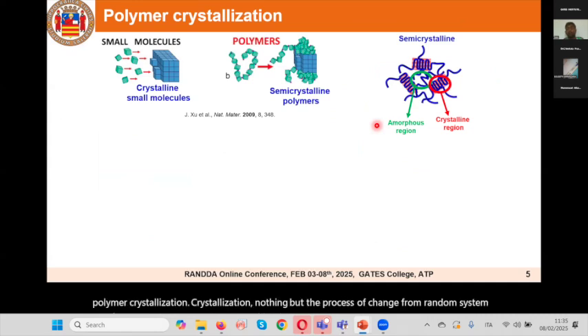That is called crystallization. Crystallization is a process completely different from small molecule to polymer. In the small molecule, crystallization is very simple because the smaller molecule has a very low energy barrier, so it can crystallize completely into a well-ordered structure, 100% like a single crystal. For example, water, a small molecule, can form a single crystal.